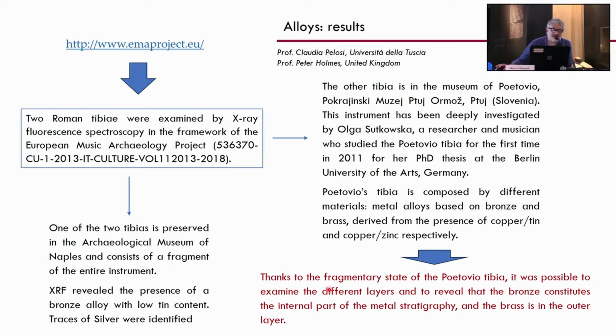And thanks to the fragmentary state of the Poetovio tibia, it was possible to examine the different layers and to reveal that the bronze constituted the internal part of the metal stratigraphy, and the brass was on the outer side of the tibia. So it was like we had two different layers, well separated. I can't show you the results because they have not been published until now, but talking with Claudia Pelosi, I can tell you that the results that I will show you now are really comparable with what they got in this analysis.